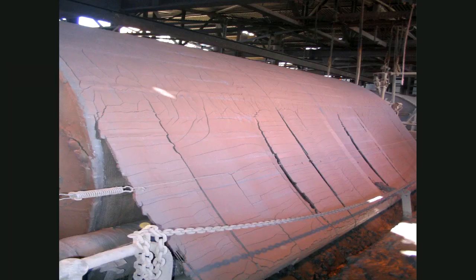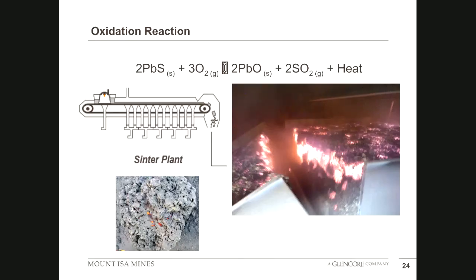So this is what your filter looks like. It's this drum filter where it sucks in all that moisture, but releases this cake. This cake then goes into the oxidation reaction, which is the sinter plant, where you supply oxygen plus a little bit of heat to get it going, and galena, or lead sulfide, produces lead oxide plus SO2 gas. And it's an exothermic reaction, so it releases more heat. So really, only around this area is where you need to ignite it. So you ignite it, get it to about 600 degrees, and then it just self-sustains. You need no more management whatsoever apart from your oxygen.